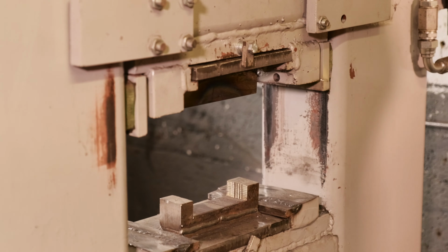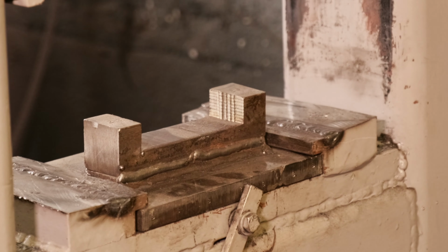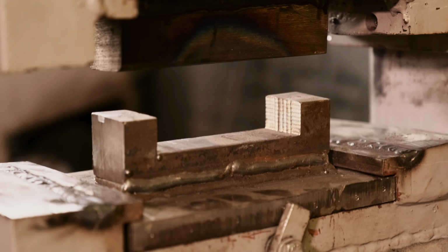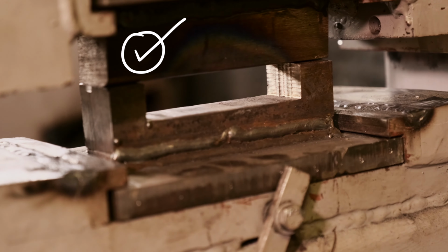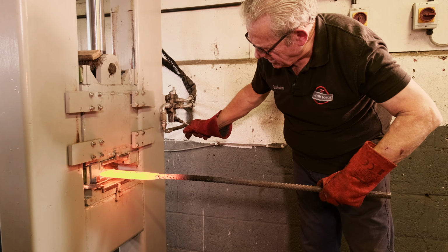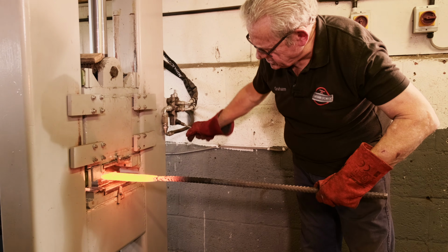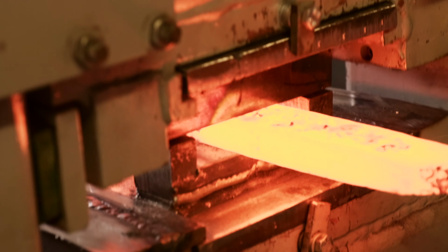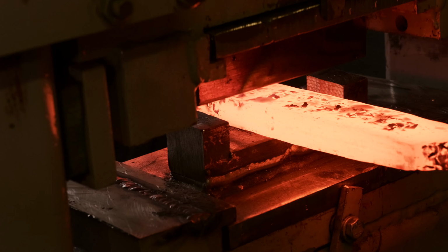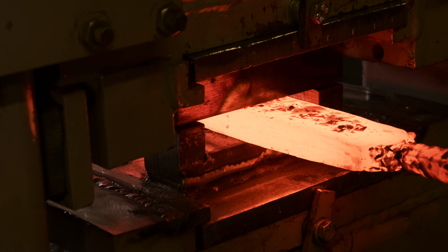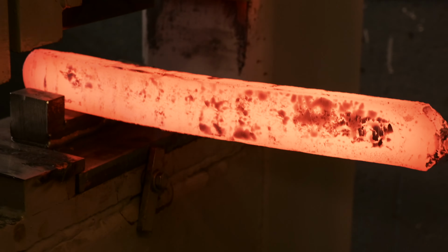You see now with this die, we've got 2 little stops on either end, so I can bring it down and she'll land on there. And I just can't make it any thinner than that. That helps me to control the thickness down to about where I want it. So I'm pushing it down hard now, small little bites, and that's setting that thickness to around about 20 millimeters. That's it. It's a nice even thickness now.